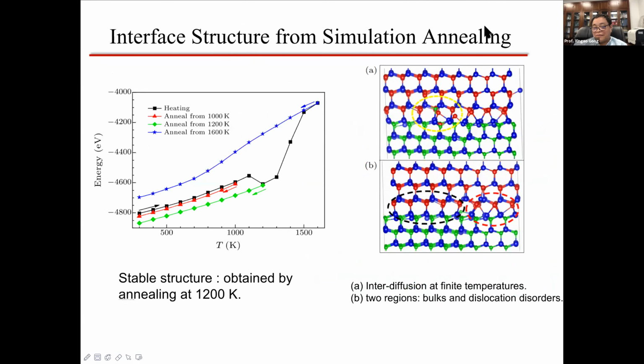So we use simulated annealing. That means you keep heating up the sample and see how the structure changes. If you look at the energies, they change smoothly up to some temperature, and then the energy drops down. That means the structure has completely changed. If you then cool down from this high temperature, you will get stable structures. In this case, you find the interface structure is quite interesting. At high temperatures, the interface shows atom diffusion, for instance the sulfur diffusing into the